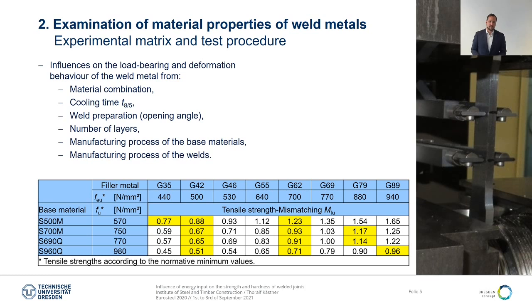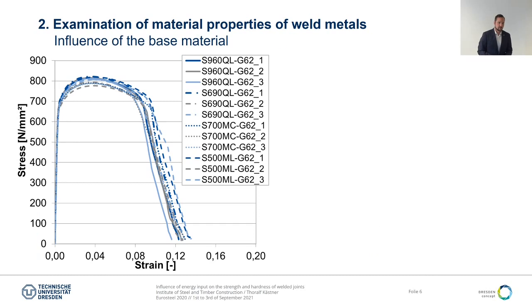Furthermore, we examined the influence of the cooling time, the weld preparation, in this specific case the weld opening angle, the number of weld layers, and the manufacturing process of the base metal. As you can see, we have both thermomechanical rolled steels as well as quenched and tempered steels, and also the manufacturing process of the welds. Most of our welds were fully mechanized welded, but some of the welds were also welded by hand in construction workshops.